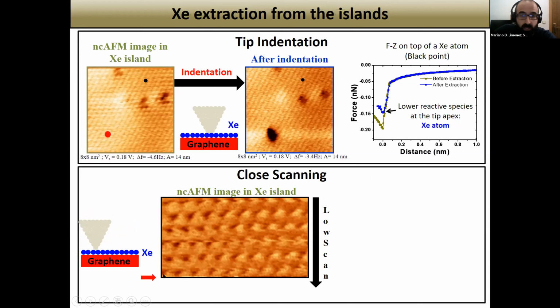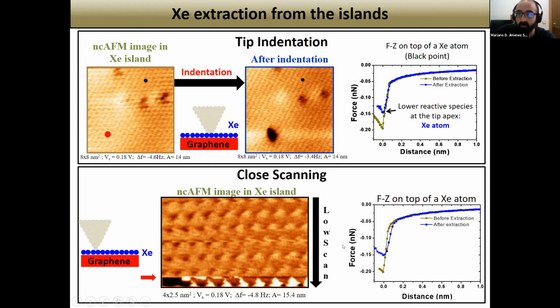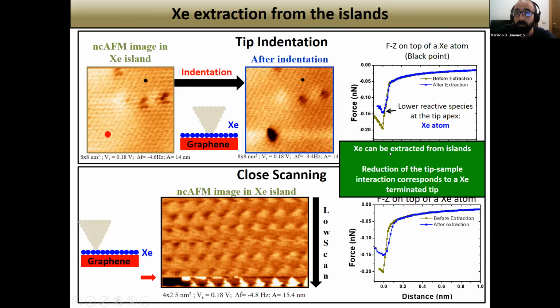Well, we obtain images like this where we can observe the xenon atoms. And in a given line, we observe the appearance of a xenon vacancy, which indicates that the xenon has been extracted from the layer, and a change in the resolution, which indicates that the tip has changed. And how does this change look on the force distance curve? Well, again, we have characterized the tip before and after the extraction, and again, we observe a reduction in the maximum attractive force, which reinforces the idea that we have a xenon atom on the tip apex.